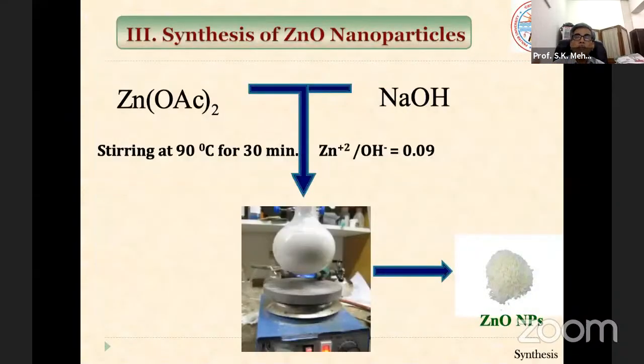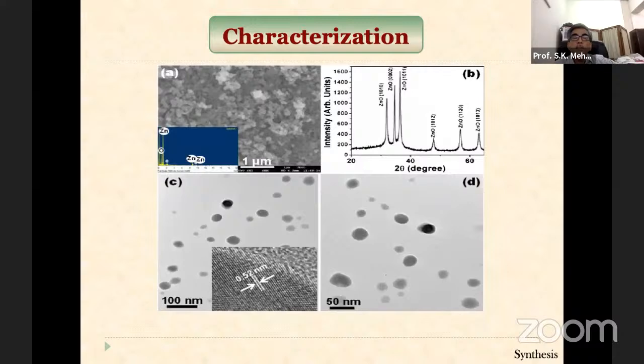Again, I'm giving you a very simple method initially, the synthesis of zinc oxide nanoparticles. I think many methods are available. The simplest: you take zinc acetate and sodium hydroxide and just stir at 90 degrees for 30 minutes, and you'll get zinc oxide nanoparticles. Characterize them as usual using TEM, XRD, and so on.